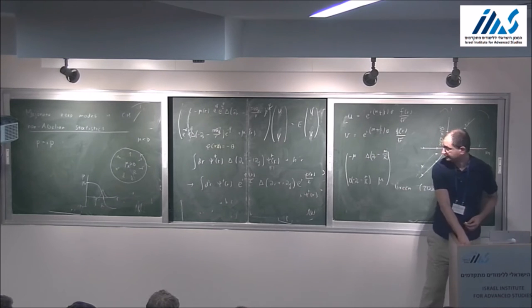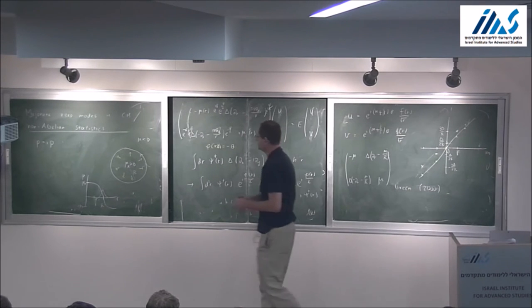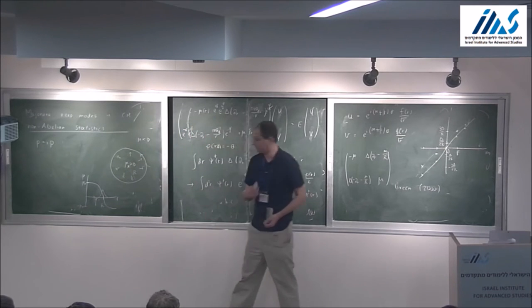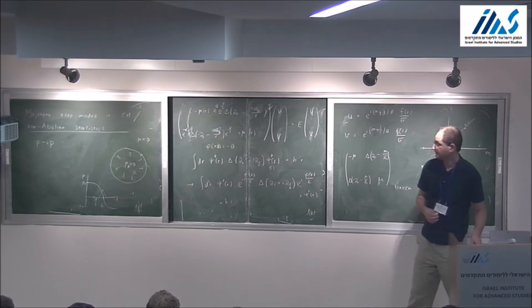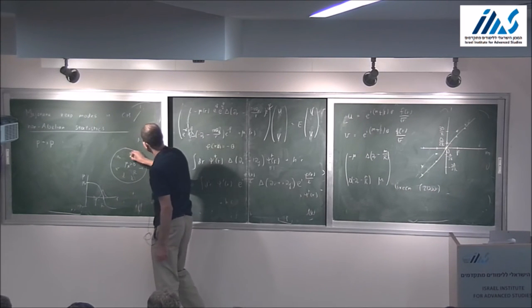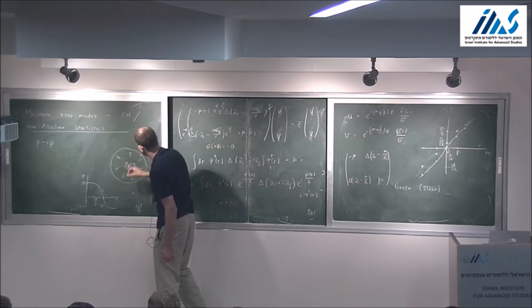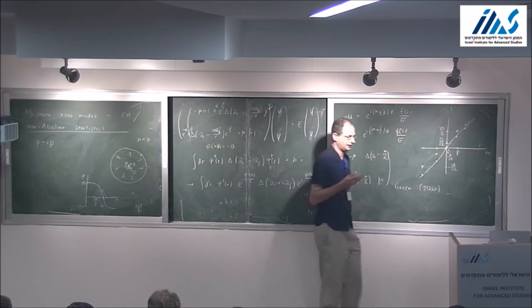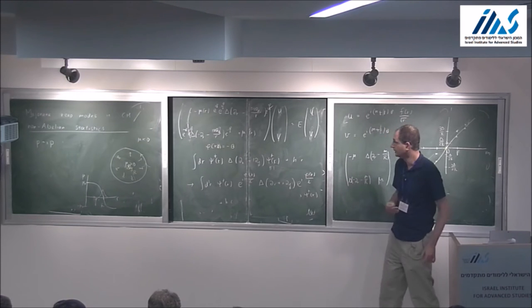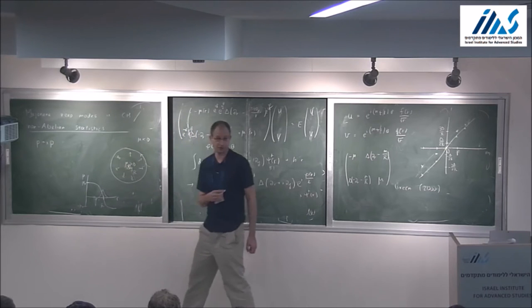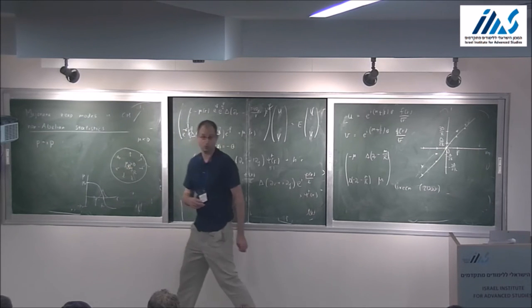So this somehow means that if we find a zero energy solution on the boundary in the configuration that has a vortex here, there actually has to be another zero energy mode somewhere. And where would that somewhere be? Anywhere in the bulk, far away from the vortex core. The vortex has a core of size xi. Anywhere in the bulk, you can say this phase variation is slow. It's essentially locally, over a length scale of xi, uniform. So the system is gapped. The only place where this extra zero mode can appear is at the vortex core.